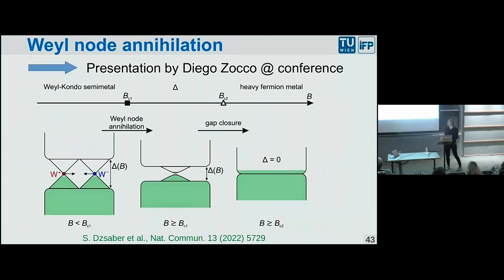Okay, so those are the things we are discussing in this program and in the conference next week. For instance, a talk that will be presented next week from one of my collaborators is about these Weyl nodes. Well, we have detected them already, but interestingly, Weyl fermions have a correspondence in the solid to the Weyl particle, and the Weyl particle is its own antiparticle in high energy physics. And that means you cannot destroy this particle unless the two meet, a particle and its antiparticle meet and annihilate. Okay, that's the only way you can get rid of these particles, which has to do with their robustness. And we have succeeded by moving them in this momentum space, making them meet, even though the rooms are full. And then if they meet, they annihilate. And that will be presented at the conference.